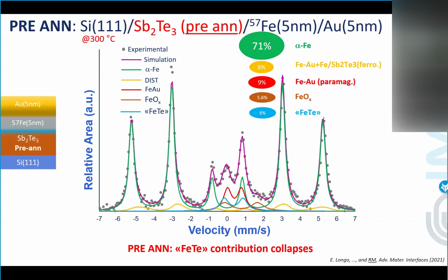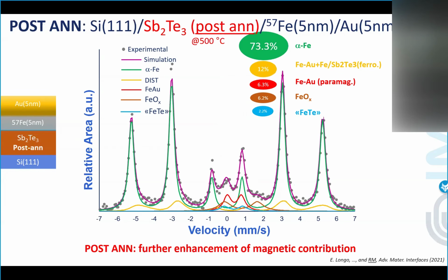But when we move to the sample where the topological insulators start to be optimized, we see that this contribution collapses. And following the post-annealing, it goes even better. So we basically restored, at the interface between iron and antimony telluride, a sort of reference situation for what concerned the properties of iron. So we were happy, and we were ready to probe spin charge conversion in this kind of heterostructure. And we start from FMR.